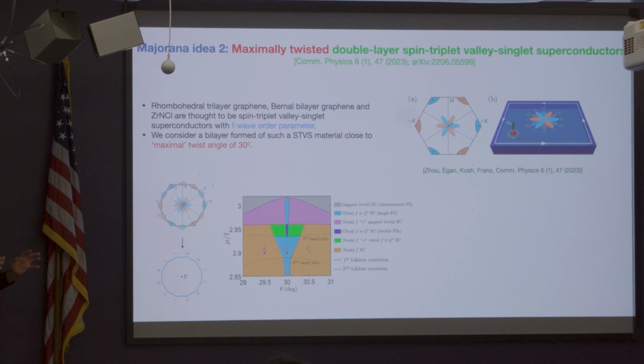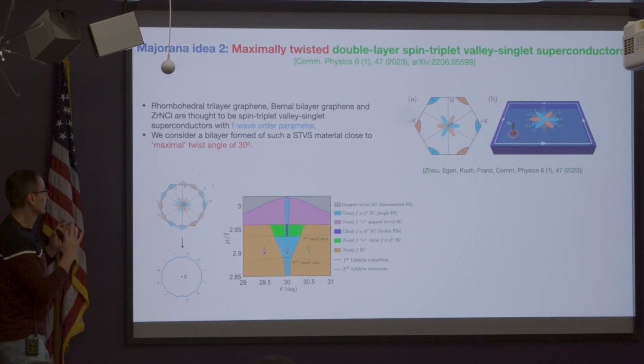So that's a gapless superconductor, which is really not interesting for the purposes of having Majorana fermions or anything like that. However, there is an interesting part of the phase diagram, which is this light blue. This light blue, which occurs here and in a fairly large area down here. And this is the chiral F plus iF prime superconductor that occurs on a, so to speak, single Fermi surface.